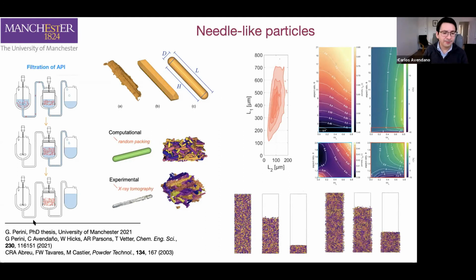So that was the PhD dissertation of this excellent student, Giulio Perini, who is working now for AstraZeneca as well. He did a lot of experiments with glutamic acid and other molecules that typically form needles. So this is the image that we obtained from X-ray tomography of one of the crystals. Typically, these particles have different facets. So we try to represent ideally that particle with this image here.